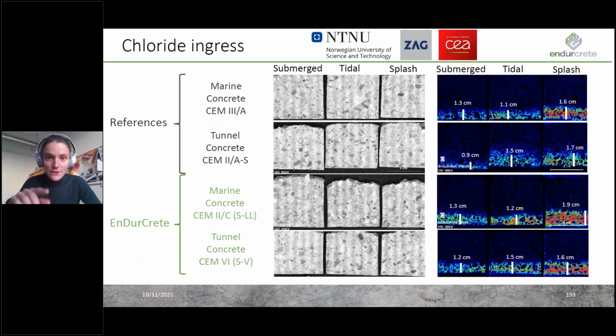I have to say that all these samples have been exposed to chloride from the bottom, so chlorides have ingressed from the bottom part of these samples inwards. To make the ingress depth of these chloride maps a bit clearer, I've added little white bars that give you an indication of how deep the chlorides have penetrated into the concrete, and also which depth they represent. If we compare the columns, the submerged, the tidal, and the splash samples, we can see that the samples exposed to the splash zone tend to have the highest ingress. So the splash seems to be the worst zone, at least at the Kirk exposure site.